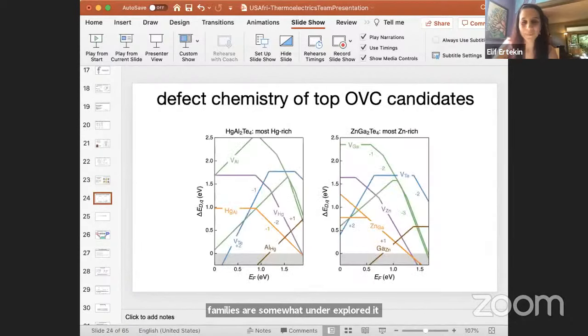Okay, and this is my last slide. Here is where we move on to the dopability of the materials. We take the most promising compounds, the ones that show a good quality factor, and are either predicted to be on the hull or not too distant from the hull. And we determine their defect chemistry through defect calculations. So I'm showing 2 examples here in the 124 family.